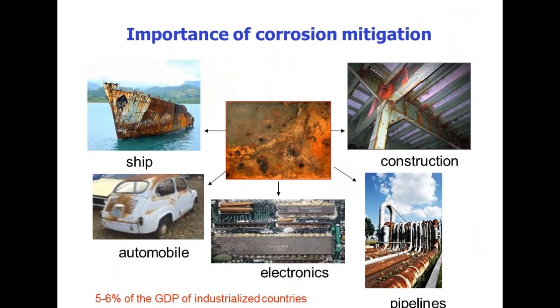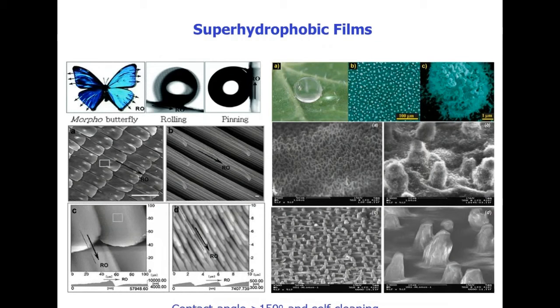Now let's turn to corrosion, a very important industrial problem which consumes about 6% of a country's GDP. Industrial coatings mean you want to protect against the environment, whether it's marine, high humidity, temperature, or flow conditions. In this case, there are things that we can use to improve the performance, such as nature-inspired superhydrophobic films. This is observed in many types of surfaces and structures, ranging from plants to insects, where we can observe their resistance to wetting based on a combination of Wenzel or Cassie-Baxter approaches, a modification of Young's equation. Here are SEM images of different structures that are able to self-clean by preventing wetting by water in the first place.